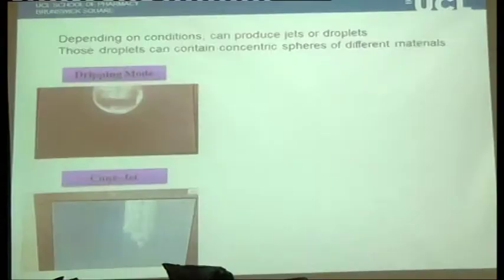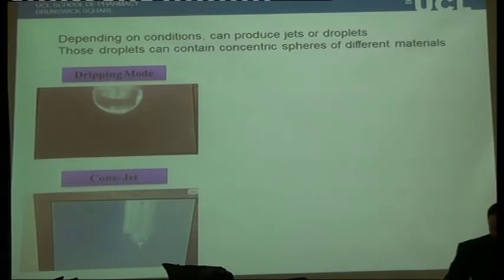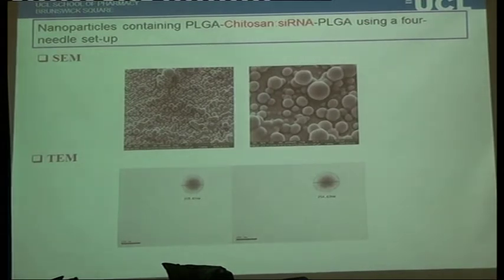If you look carefully at the images, you can actually see the separate layers being formed in the particle, which is quite nice. You can also change the parameters — such as concentration or the electric charge across the tip — and produce a fibre system instead, so the same setup produces both types of material. We can certainly produce particles at a pretty high rate. With just that simple system we are still talking about milligram scale, but the point is that it's theoretically scalable.